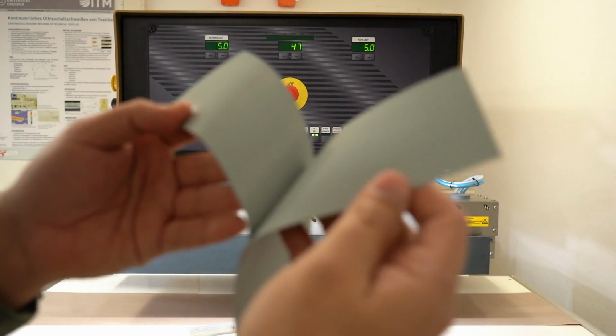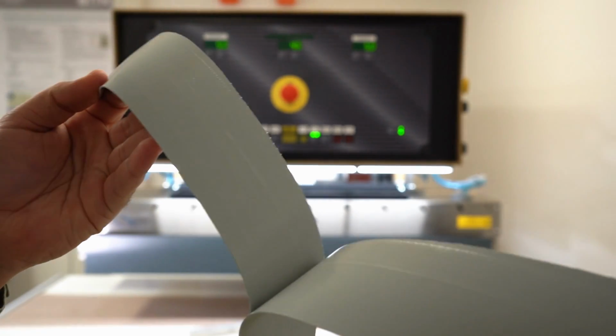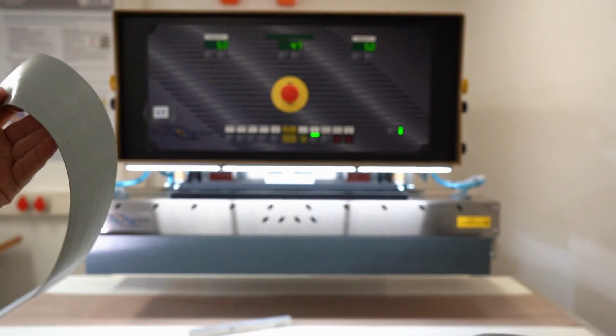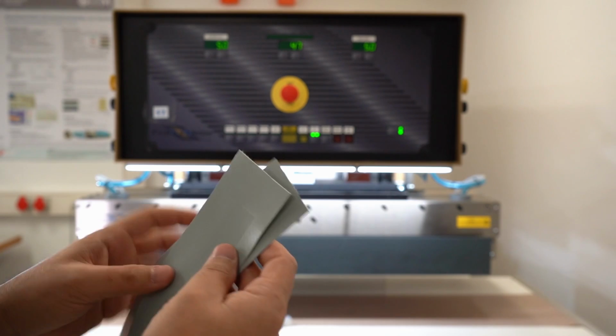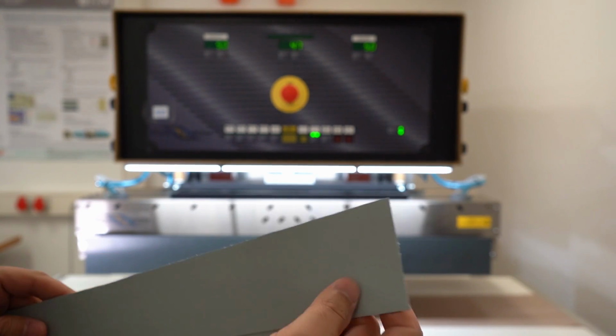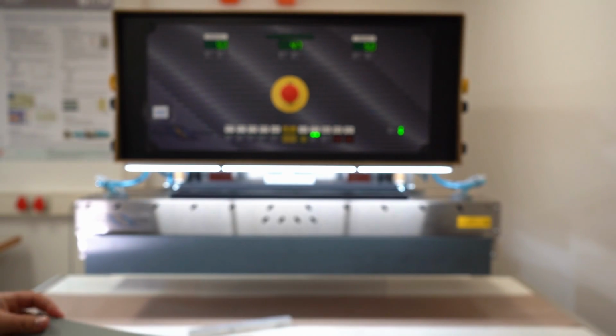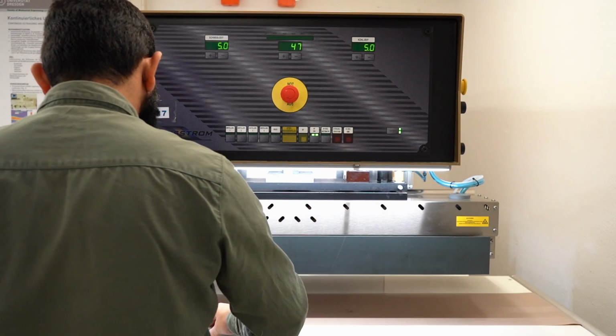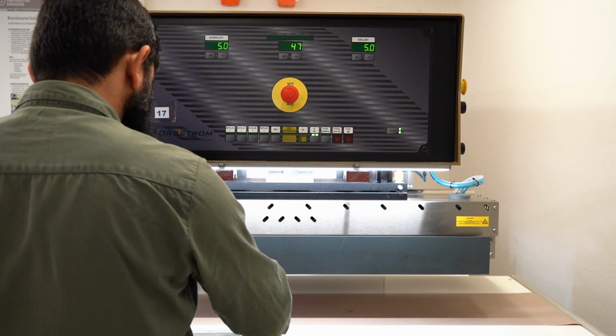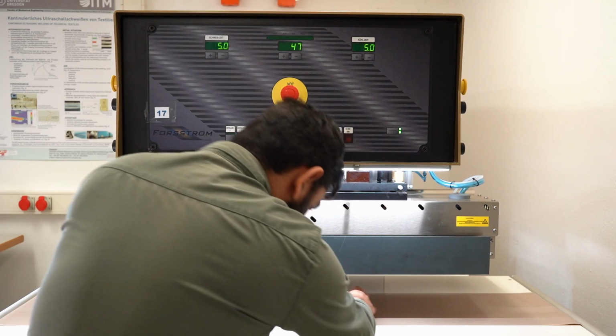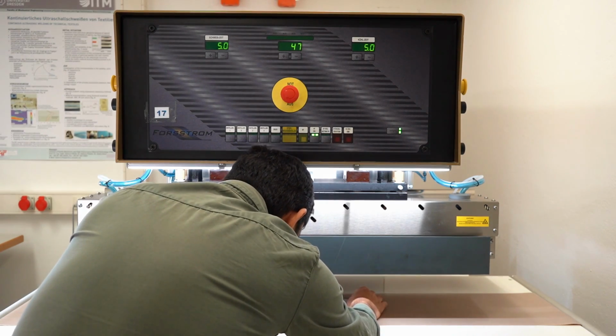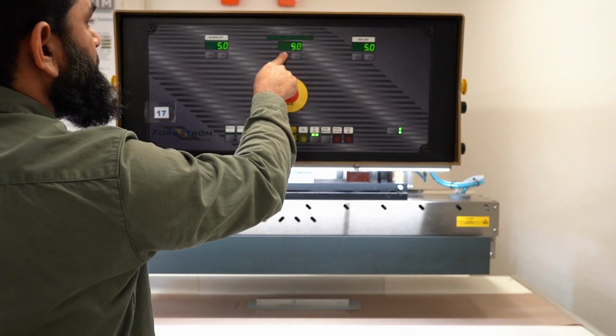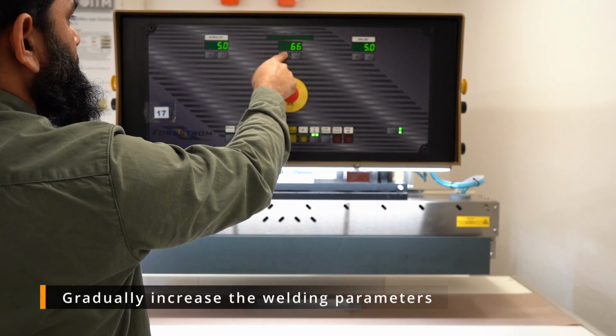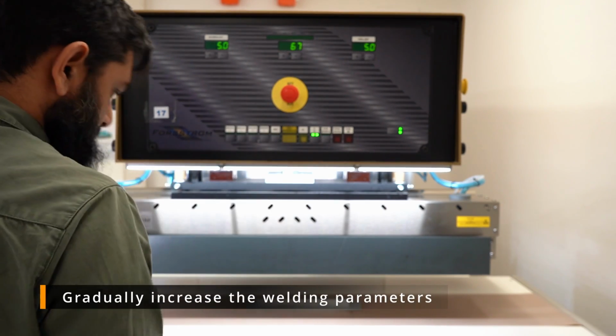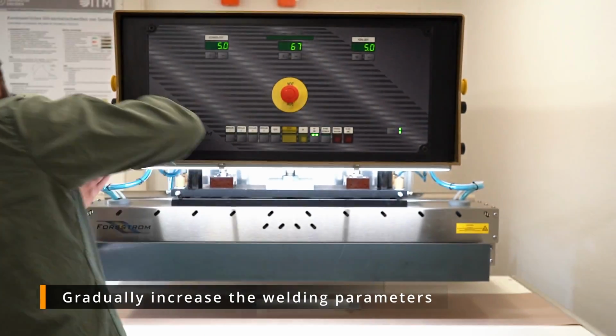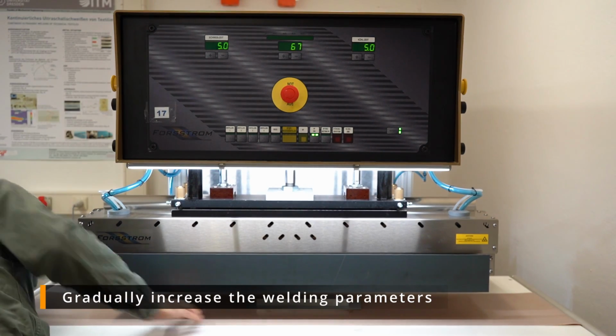I'll take the seam and see if the weld has taken place. Apparently nothing has taken place, so it's just a little bit of adhesion between them, but mainly it's not because of the welding or the melting of the thermoplastic material. So I have to do it again, and this time I'm going to further optimize my machine parameter. From 47 I'll go to, let's say, 67%, and again check, placing it in the middle.